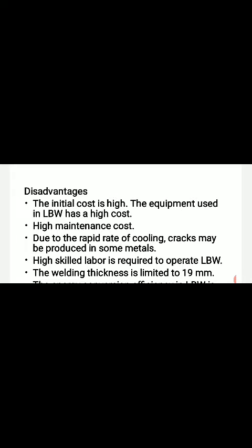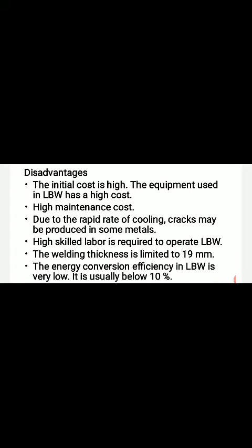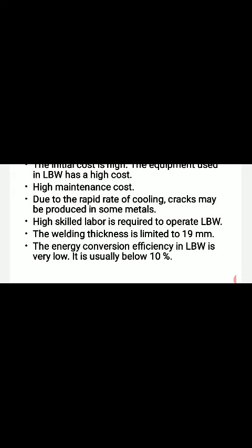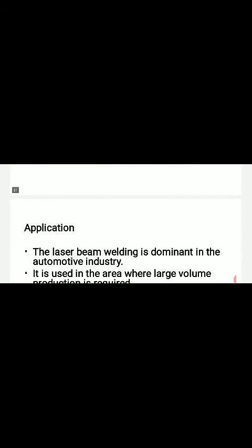The equipment used in laser beam welding has a high cost, and then there is a high maintenance cost. Due to the rapid rate of cooling, cracks may be produced in some metals. Highly skilled labor is required to operate laser beam welding. The welding thickness is limited to 19 mm. The energy conversion efficiency in laser beam welding is very low. It is usually below 10%.